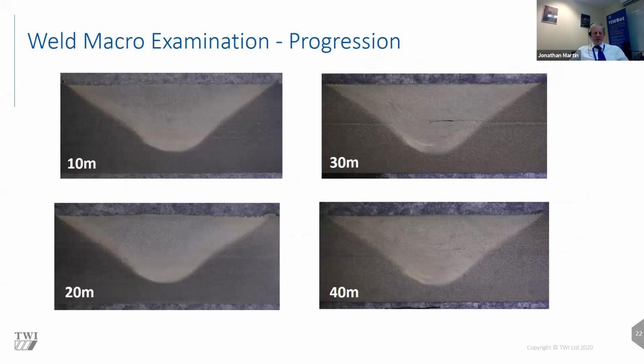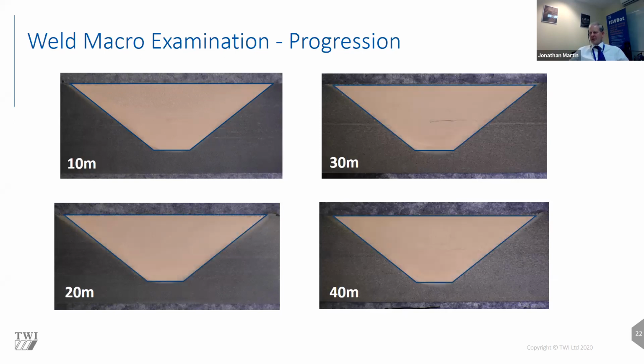We also took a macro from every 5 meters. This is just showing every 10 meters, so you can actually see in a little more detail what the weld nugget looks like. So very typical of a friction stir weld. You can see the raw material of the plate around the nugget and the TMAZ. So in order to try and quantify, are the tools mixing the material similarly, we just overlaid on this first one after 10 meters a shape to say, okay, this covered really the nugget and the TMAZ. And then if you translate that and overlay that on all the other welds, you can see how consistent the shape of that weld was, which leads us to believe the consistency of mixing of these tools was very, very good.